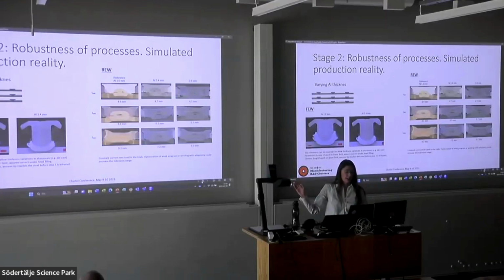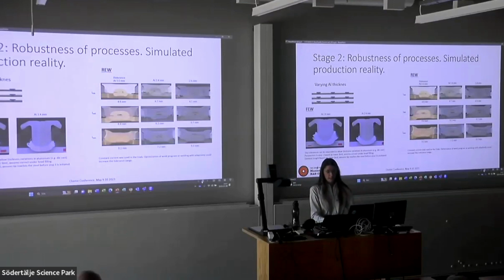And instead, when you increase the thickness, you can see maybe that the friction weld tends to become a bit smaller. And in this case, you should modify the process a bit depending on the thickness variation in your cast component. So, for example, the element length itself should be determined by the thickest part in the aluminium component. For resistance element welding, we actually did not see any influence on the nugget size testing with different aluminium thickness and at different current. It is also worth mentioning that in this case we used constant current, and there could be possible benefits using adaptive welding system.